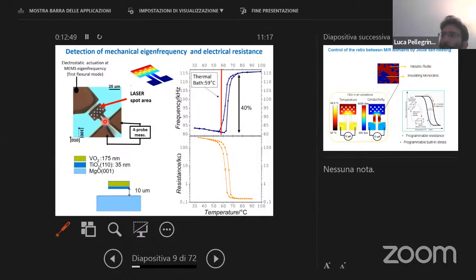This is due to the fact that by changing the temperature, this film changes both the electrical resistance and the internal stress, due to the change of the lattice structure. And as you know, stress can change the resonance frequency of a freestanding structure. If we have a microbridge, for example, and we stress it, we can change the resonance frequency of a wire or of another structure.